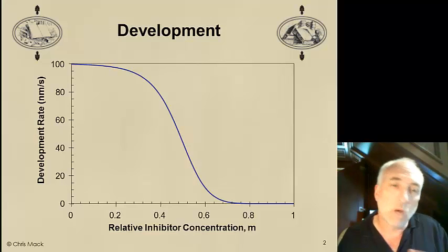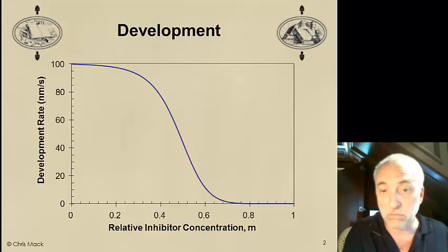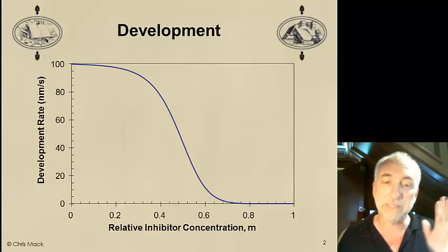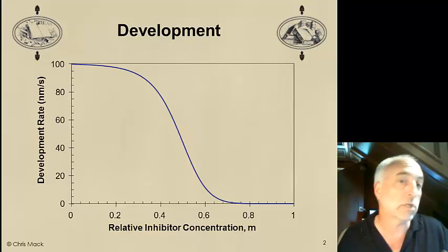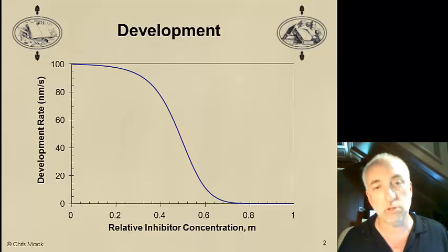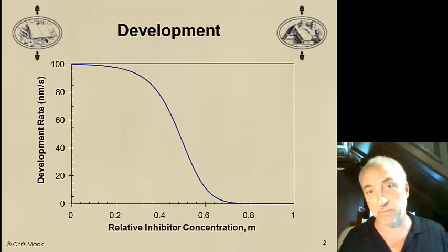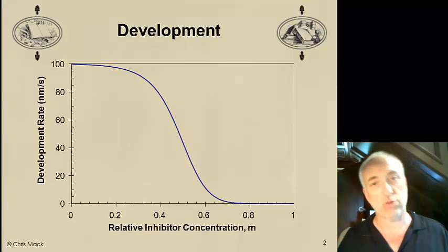But what do we want in the in-between region, at the edge between where the resist is soluble and where it's not? Well, what we'd like is a very sharp distinction between the region that's soluble and the region that's not. We want a sharp edge. We want step functions of photoresist when we're all said and done. To achieve that, we need highly nonlinear development behavior.